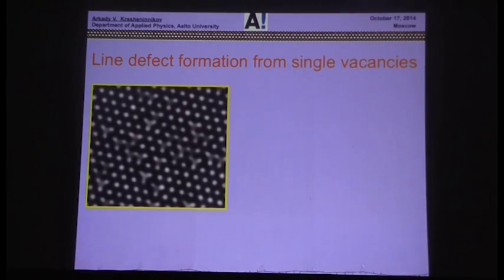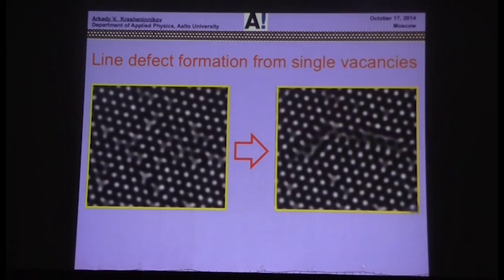The more interesting question is the actual mechanism of transformation. If you take one slide from the movie, basically like that, and zoom it up, and 1 second later, you see that many vacancies in the upper part of the image collapse into line defects, while the vacancies in the lower part of the image are still there. This vacancy is still here, so nothing happened in the lower part.